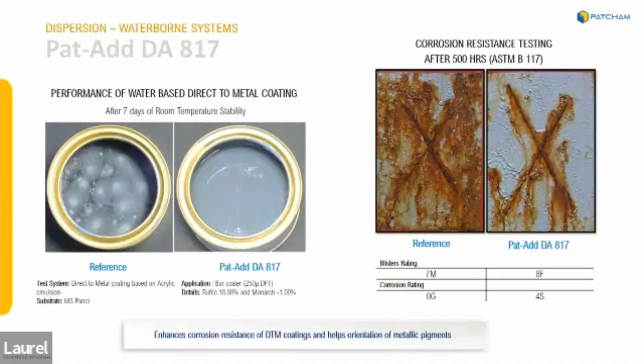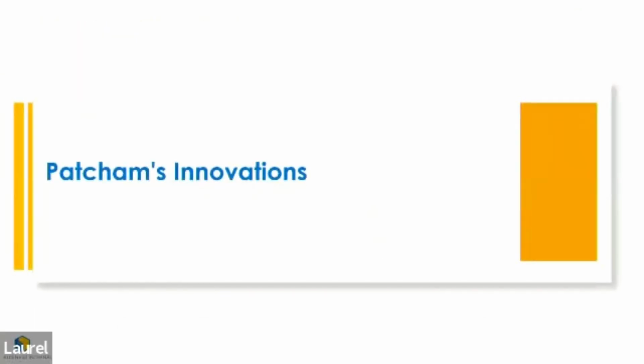And then the impact on, typically these would be primers, which have high content of high density pigments. These tend to separate and relocate themselves due to their gravitational preferences, and you can see from the example of the can, these are stability cans that have just had the lid off and they're unstirred. The uniformity of the particular product and its ability to provide corrosion resistance by keeping the pigment particles in their proper distribution.